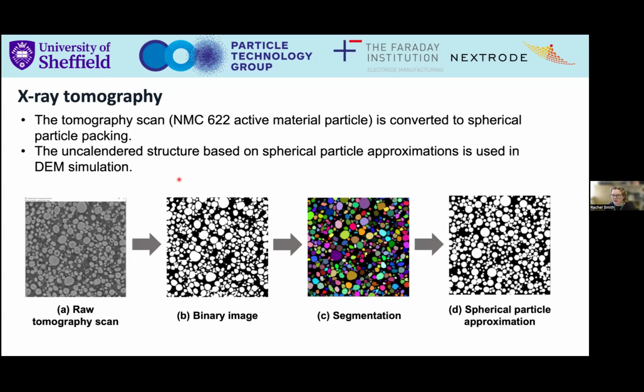image, and then eventually what we do is we replace each of the particles in our tomography scan with a spherical particle. Now the reason for that is because spherical particles are by far the easiest type of particle to use in DEM simulations, but we're not relying on that. I'll show you a little bit later how we've also double checked our assumption that that is okay.